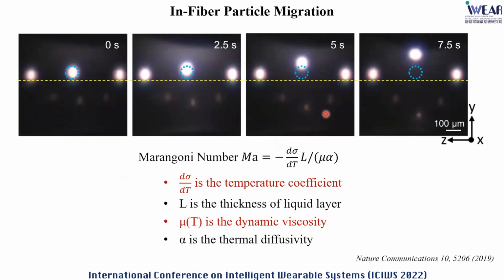As a demonstration, we show three semiconductor spheres inside the fiber, and simply by heating the center one, because of the thermally induced surface tension gradient, only the center one starts to move upward. This is also considered a type of Marangoni effect. And how can we use this to assemble the in-fiber junctions?